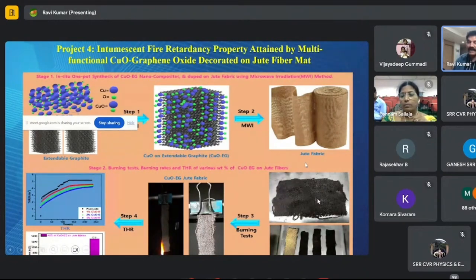You can see it looks black, but at different weight percents, the pure one is almost brown because there is no deposition, and the weight percent gradually increases from 1 to 3 weight percent. It shows the morphology and the image shows the black color. And when you start burning in the vertical burning test, the fire is not catching, even though it is incandescent on the surface. The jet of heat or flame is not catching fire because of the heat shielding coming from this material. You also observe these two graphs showing that the heat release rate is very slow compared to the pure material after deposition of CuO graphene oxide. This is going to be published soon in a top rated journal.